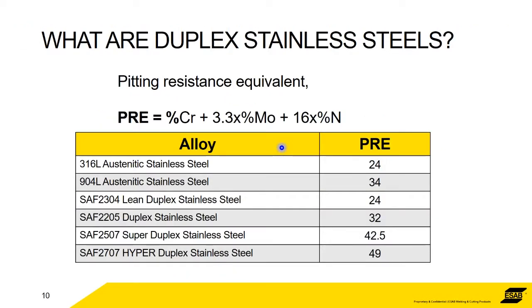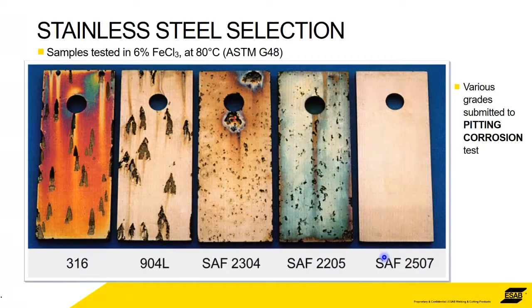On the scale, if you want to see where something that you may be more familiar with, like a 316 austenitic stainless steel, sits, using this formula again, the resistance to pitting for 316 is a number 24, whereas a standard duplex 2205 stainless steel is 32. And again, we talk super duplex and hyper duplex. What effect does that have? A standard corrosion test for all the families of stainless steels is a G48 corrosion test.